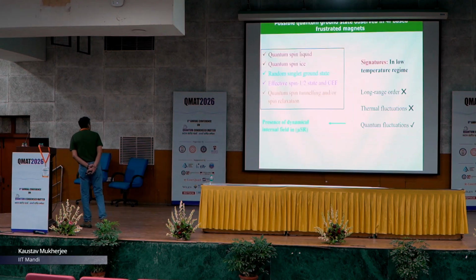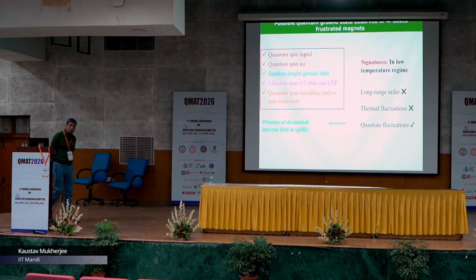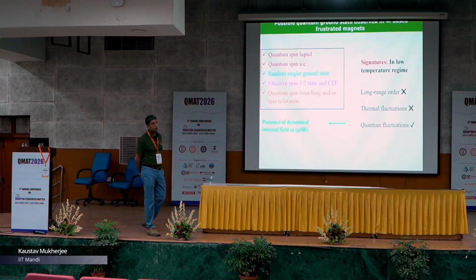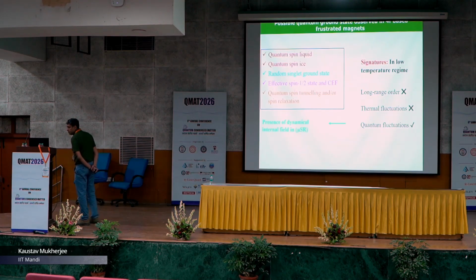Okay. Now, I have earlier mentioned that there is a suppression of long range ordering, and it gives rise to novel magnetic phases. So what are the possible quantum ground states which are observed or reported in 4f based frustrated magnets? One of them is the quantum spin liquid, which we all know is a highly entangled magnetic state where spins do not order down to the lowest temperature. Then we can get quantum spin ice behavior in such systems. Then there can be random singlet states, effective spin states, which are also reported in such systems, and also we can have spin tunneling and spin relaxation effects.